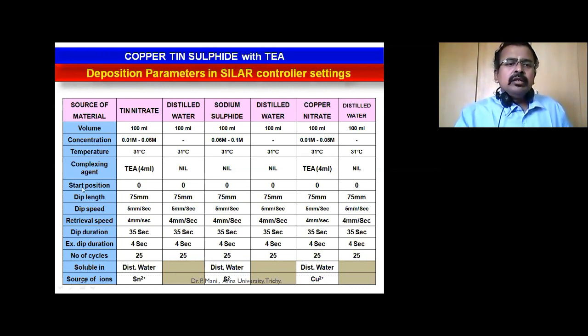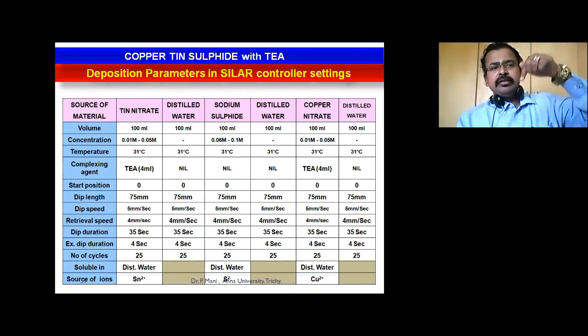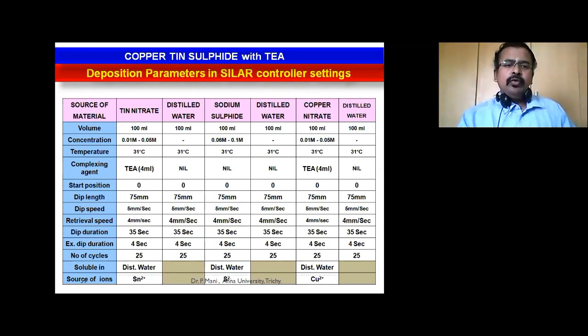Then we may fix start position as 0. Then dip length of 75 millimeters. Dip speed, in the sense of immersing the glass plate inside the beaker slowly, that is 5 millimeter per second. And retrieval speed, retrieving the glass plate from the beaker, that is 4 millimeter per second. Dip duration, that is immersion time, 35 seconds.